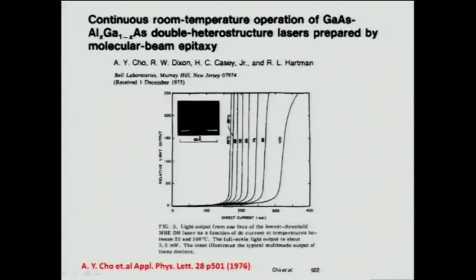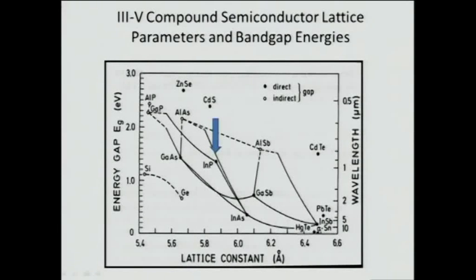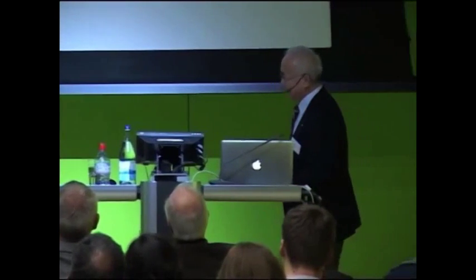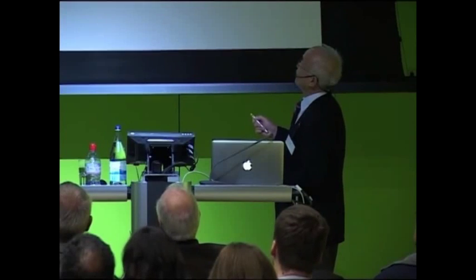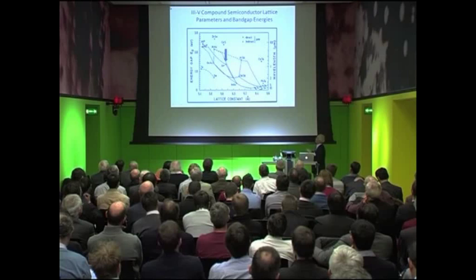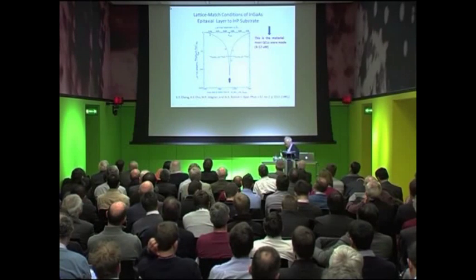And by the time of 1976, in collaboration with Dick Dixon and Craig Casey, we made the first continuous room temperature operation of gallium arsenide, aluminum gallium arsenide double heterojunction injection lasers. And that was the encouragement to me that if we work hard enough, we can finally achieve what earlier looked like impossible. We further developed from gallium arsenide, aluminum gallium arsenide, extending to growth on indium phosphide substrate, because at that time, a lot of these devices were going to indium phosphide, making 1.3 micron devices for communication systems and so on. So we got pressure to grow on indium phosphide substrate. We had to make indium gallium arsenide or indium aluminum arsenide lattice matching to indium phosphide, which is a little harder for me to handle, this kind of material.